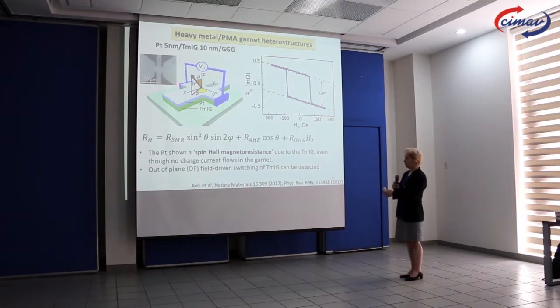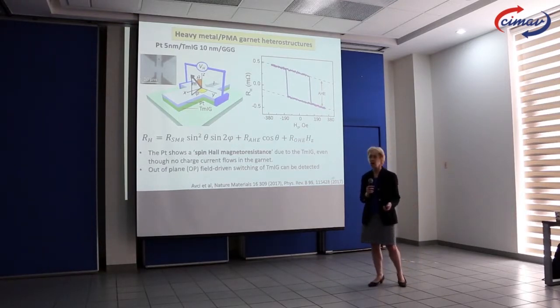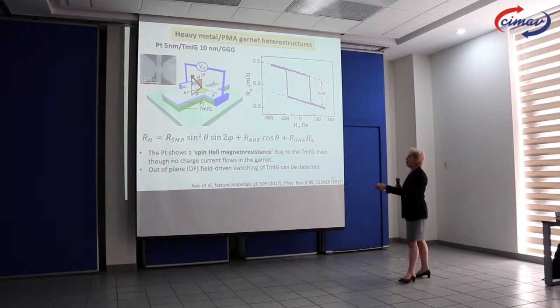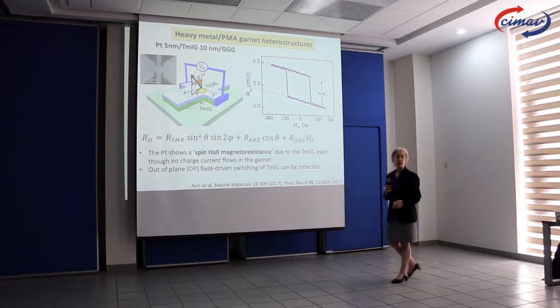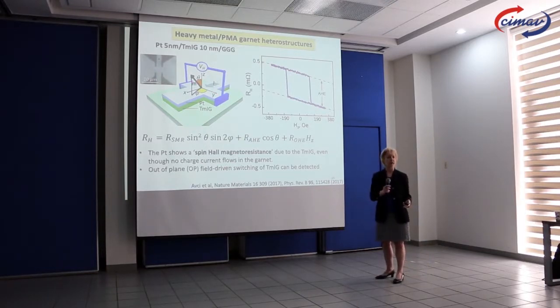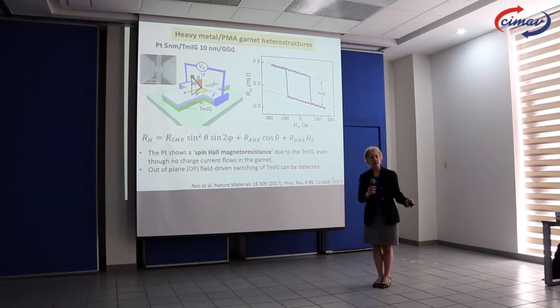So we make a Hall cross. This is a garnet cross with a platinum cross. And we're going to flow a current one way and measure a voltage in the other direction. So just a standard Hall cross type of geometry. So what do we get for the Hall resistance in the platinum? If it was just platinum on silicon, you'd say, we'll get the ordinary Hall effect. And that's the slope here, the ordinary Hall effect.